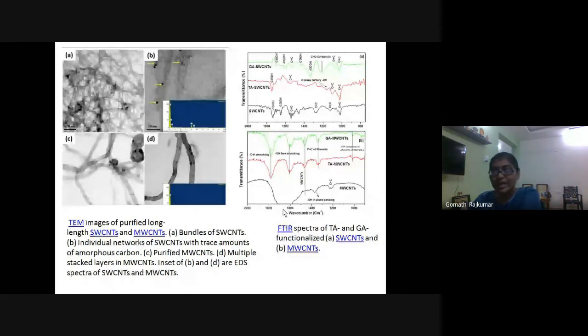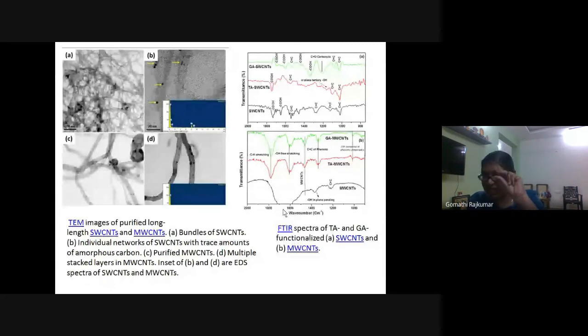Okay. So we actually synthesized both single-walled carbon nanotube and multi-walled carbon nanotube, where you can see that all these are bundles of single-walled carbon nanotube. And here this is an individual network with traces of amorphous carbon.